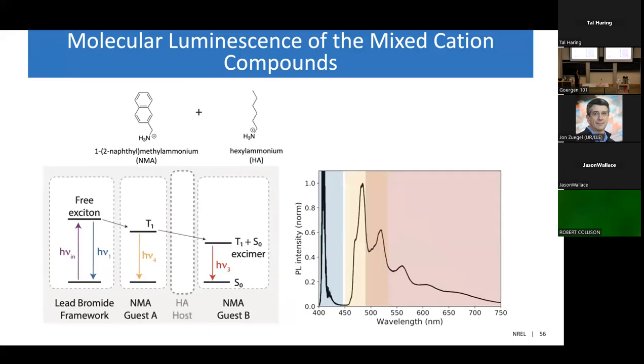And then finally, when we mix the two organic molecules together, we see emission from 3 different species. First, we see pretty significant inorganic exciton emission. Then we also see naphthalene monomer phosphorescence, which is the part shaded in orange. And then we also see some excimeric contributions as well, which is the part shaded in red.